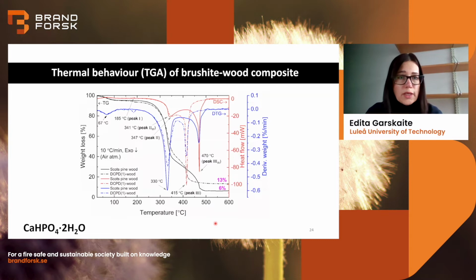So we also did studies of thermal behavior, and I will just mention a few things. When we compare unmodified wood with modified wood, we see this black curve, and then the broken black curve, which is showing weight loss when you're increasing temperature. And what we saw is that the residue mass of mineralized wood is higher compared to unmodified wood. So that's also one thing showing us that we managed successfully to make material inside of the wood matrix.